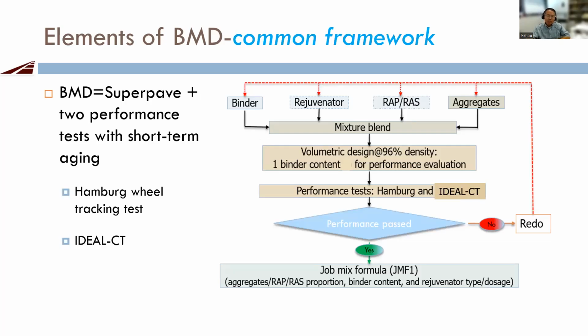So how can we put everything together? This is the BMD, basically equal to the current SuperPave volumetric design, plus 2 performance tests with short-term aging. I'm picking here the Hamburg wheel tracking test and ideal CT. Basically, this is the basic process, which everybody is very familiar with. In the volumetric design, you pick 96% density, you get a binder content, and then you run your performance tests. Are we passing my Hamburg test and the ideal CT test? If performance passed, then you go to your job mix formula. And if not, you go back, change your binder, change your gradation, reduce your RAP percentage, or use a rejuvenator and do it again. That's the most common framework people are using right now.